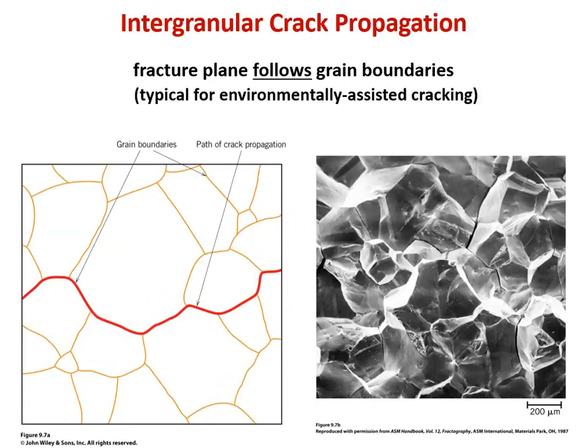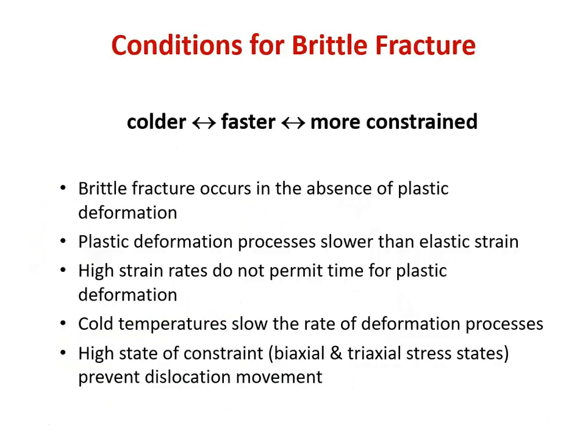So we can contrast that with intergranular, with again the schematic on the left-hand side, and then a top-down SEM shot on the right. And this is the real sugar crystal looking appearance, where you are literally seeing almost the 3D surface of the grain structure of the material. This is very, very characteristic of hydrogen embrittlement, hydrogen-induced cracking, and stress corrosion cracking. So when we see this on a failure surface, we immediately start wondering whether or not this material was used in the wrong environment, especially for metals.